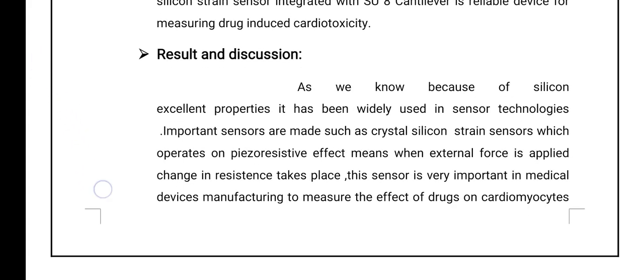Now we will move to results and discussion. In short, the conclusion is, by replacing the traditional metal strain sensor with a single crystal silicon strain sensor, we greatly improved the sensitivity of detecting the force of cardiomyocyte contractions. The experiments show that the single crystal silicon strain sensor can detect extremely small forces as low as 0.02 micronewton and is nearly 17 times more sensitive than metal sensors. We also use the integrated SU8 cantilever to measure how verapamil and isoproterenol, these two drugs, affect the contraction properties of cardiomyocytes.